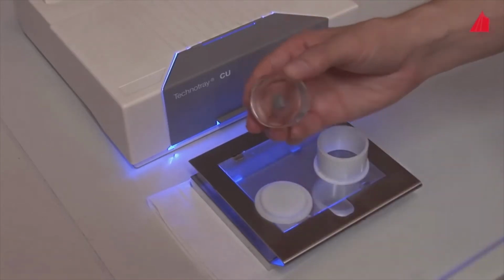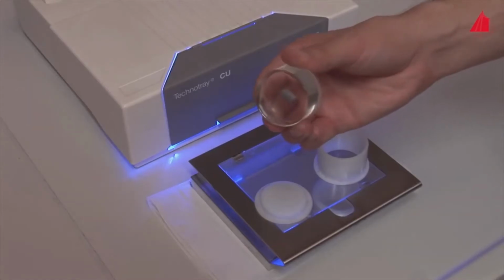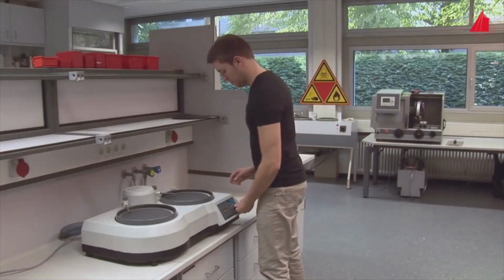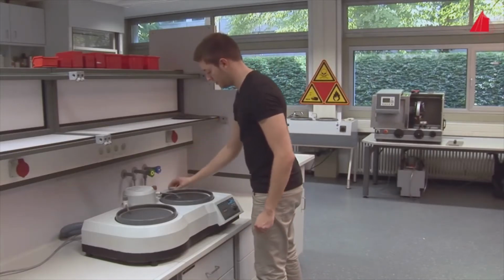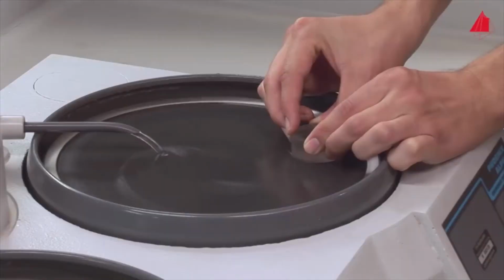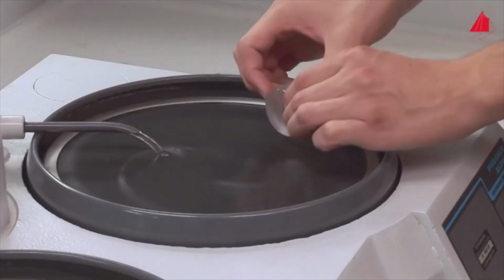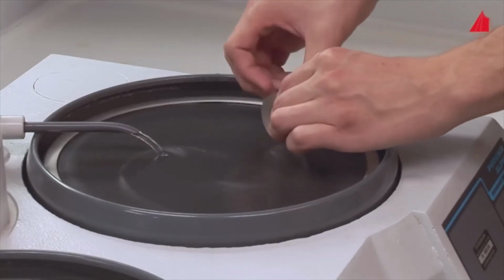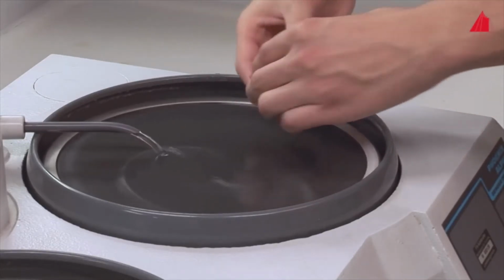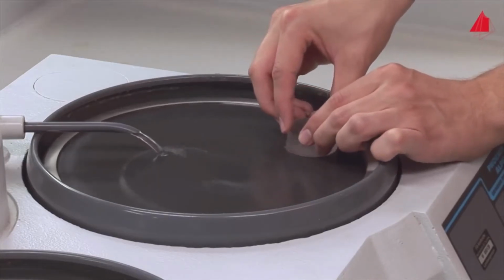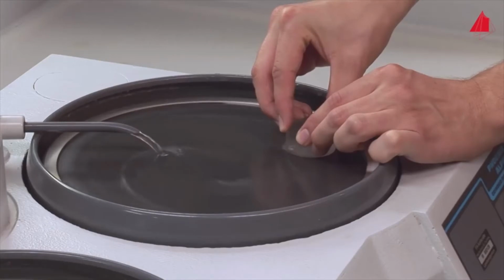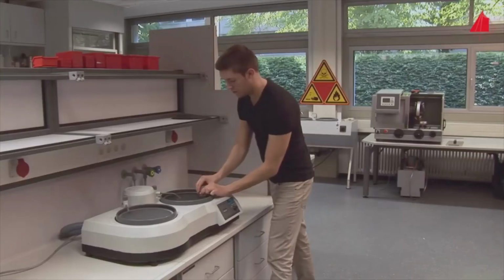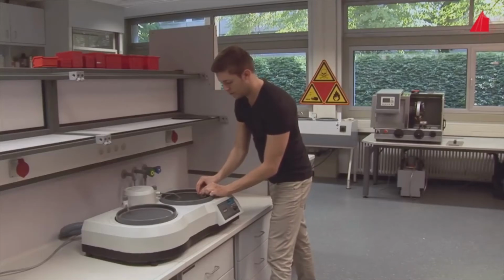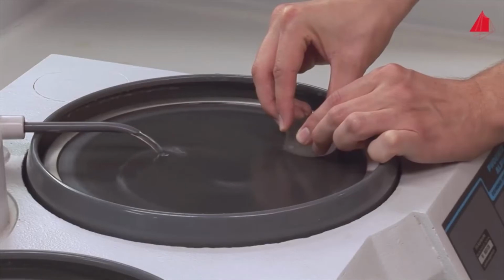Because the top surface is still uneven and slightly sticky, the material tester grinds it there until it is even. He uses a rotating water-lubricated disc equipped with coarse-grained silicon carbide paper. The circumferential surface is slightly ground as well to ensure a clean specimen. Now comes the most important part, the preparation of the intended plane of examination. Our material tester begins with comparatively coarse 180 grit abrasive paper. He makes sure to press the specimen calmly and evenly onto the abrasive paper, compensating the tendency for the sample to tilt. He also makes sure not to grind his fingertips accidentally.